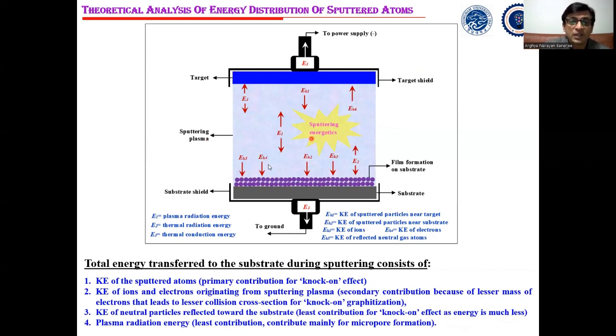For that, we first considered the energetics of the sputtering system. Generally, the total energy transferred to the substrate during sputtering consists of kinetic energy of the sputtered atoms, which is the primary contributor for the knock-on effect, then kinetic energy of ions and electrons originating from sputtering plasma, which is the secondary contributor for this graphitization. Third is the kinetic energy of neutral particles reflected towards the substrate, which is the least contributor towards the knock-on effect, and the plasma radiation energy, which is the least contributor for the graphitization, but the main contributor for activation for porous carbon network formation.